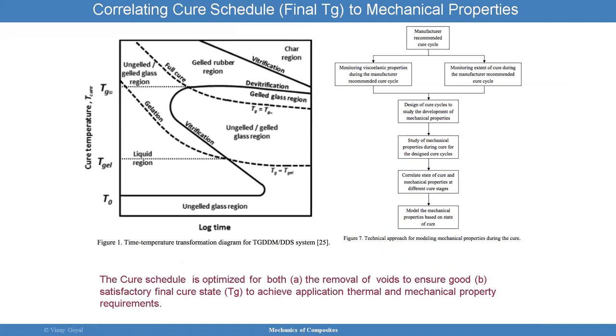So how do you correlate cure schedule to the mechanical properties? There is a connection. The cure schedule is optimized to get the best performance out of the composite. For both, A, you can remove the voids to ensure it's good, and B, make sure the final cure state is good, to achieve the thermal and mechanical properties you need. And so the bottom line here is, you've got to make sure that you're achieving the right mechanical properties by making sure that voids have been removed.